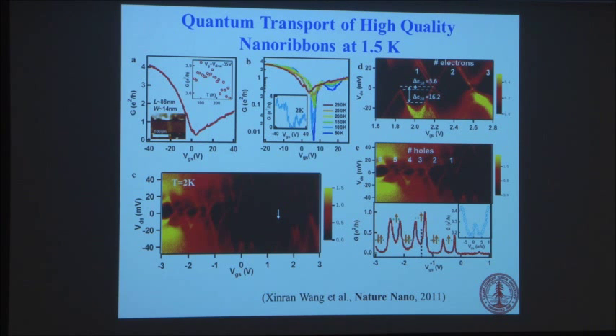So all this stuff, okay? And the data here basically shows the ribbon quality is pretty good. And you see that at low temperature, the conductance goes down to very low, okay? And that's simply because it's actually a semiconductor, okay? With a band gap of about 50 millielectron volts. So when you cool them down, they have this huge modulation of the conductance. Anyway,